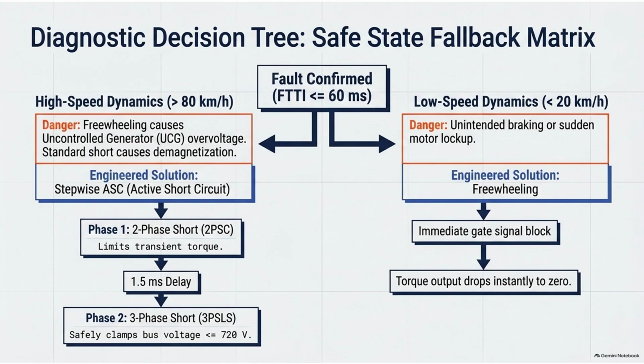Because if you do a direct, immediate, three-phase active short circuit, or ASC, you hit another wall of physics. When a motor is spinning at high speed and you instantly short all the terminals together, the massive back EMF drives an astronomical transient current strictly within the motor windings. Okay. This colossal current creates an opposing magnetic field that hits the rotor like a sledgehammer. A magnetic sledgehammer, what does that actually do to the physical components? It creates a massive transient demagnetization field.